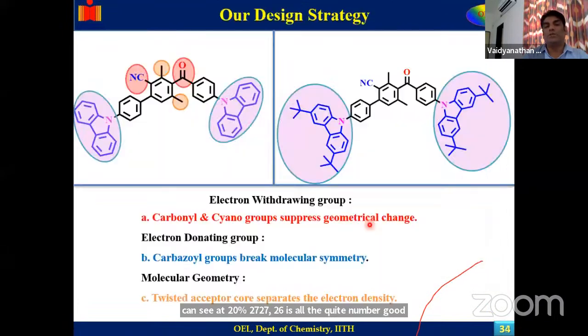So I'm going to discuss our work. We took this kind of keto molecule. In order to fine tune the band gap, we put one benzene ring, two methyl groups, one cyanide, and the electron withdrawing groups, cyanide and carbonyl, suppress the geometrical change. The electron donating group, carbazoyl group, breaks molecular symmetry. So you get a twisted acceptor core, which separates the electron density.